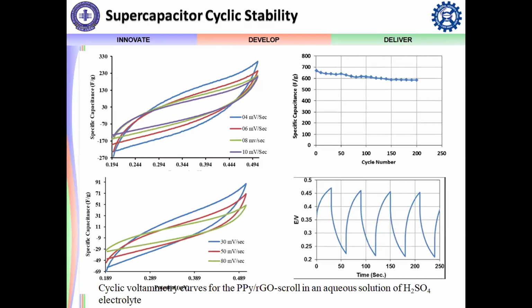So we have tested it in the two electrode method, where on one substrate this EDLC capacitor is formed, and it is tested in the presence of sulfuric acid. And we have tested cyclic stability, and the specific capacitance was quite good. It is more than 600 farad per gram. And further, we have worked on the miniaturized structure, which has further increased the specific capacitance of that material.